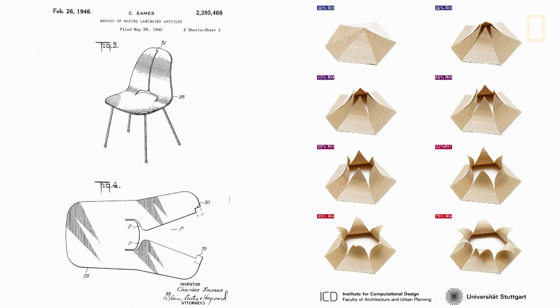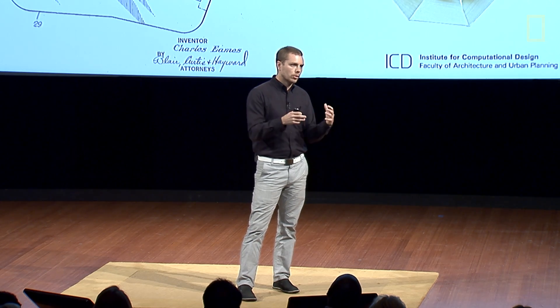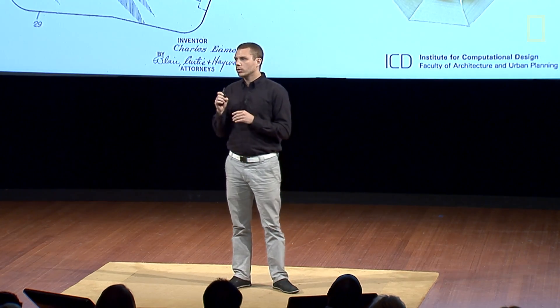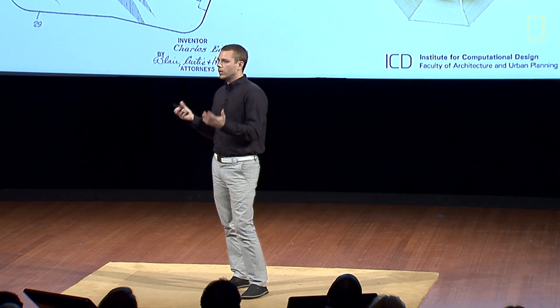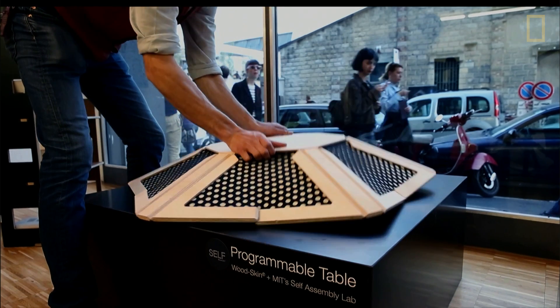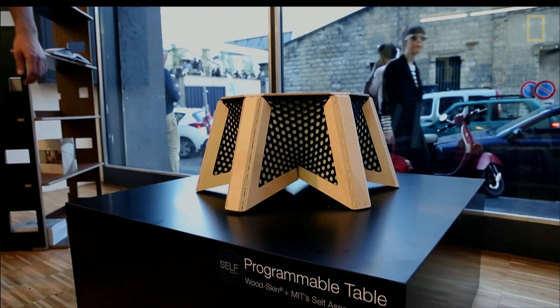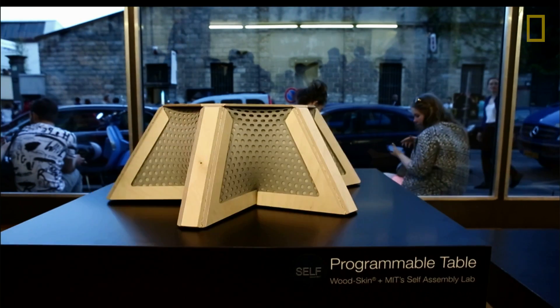But there's two main problems. One is that there's a lot of energy that goes into forcing plywood to form into arbitrary shapes — you have to force it, steam it, and have molds. The other is that you're constrained by the grain direction you can find in the forest. So we print wood. We deposit wood, chop it into a pulp with sawdust and adhesive or plastics, and we're able to print different grain directions — two-dimensional and three-dimensional patterns — that allow it to fold, curl, twist, and go from any one arbitrary shape into any other arbitrary shape.